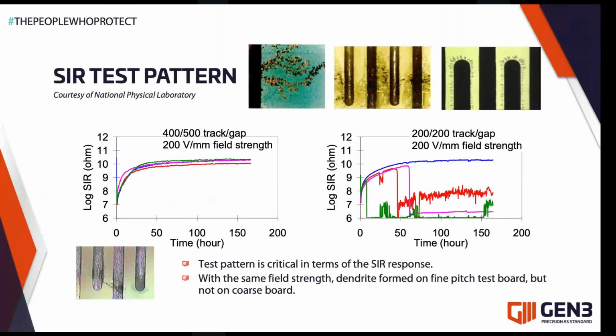We've seen one of these results before, but the important thing about these two graphs is they were both done with the same field strength of 200 volts per millimeter. But one was done on a fine pitch pattern at 200-200, and the other was done on the 400-500 with a much wider gap. And you can see that on the left SIR result, we didn't get any sort of corrosion events happening, whereas on the right graph we did. So those failures electrically are showing us effectively when a dendrite grew, and there are some images on this board showing all the different types of dendrites that we observed.